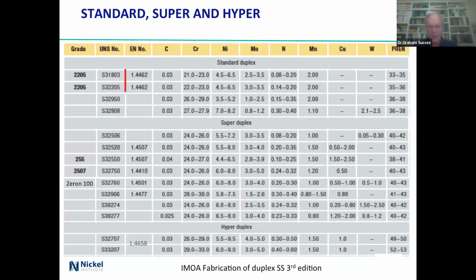Go down the bottom, and we're looking at super duplexes, and there are a lot of them, but the common ones, 2507 and Zeron 100, have got the PREs all greater than 40. There were, for a long while, things that were touted as super duplex because of the compositions, but in the standard, it didn't actually say that. And people foolishly were using things that were actually less than 40. Nowadays, most of them have a little thing in the remarks column saying PRE to be greater than 40 or 41 or sometimes 42. And right down the bottom, 2 grades and 1 supplier. And you're looking at 50 or more.